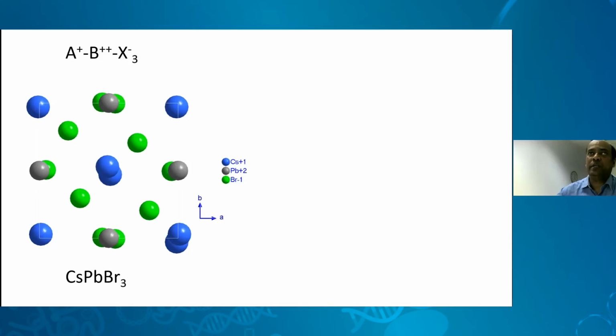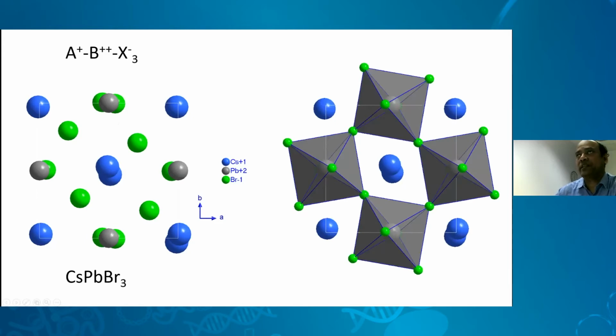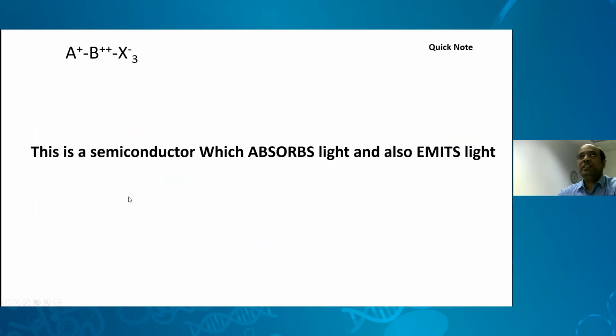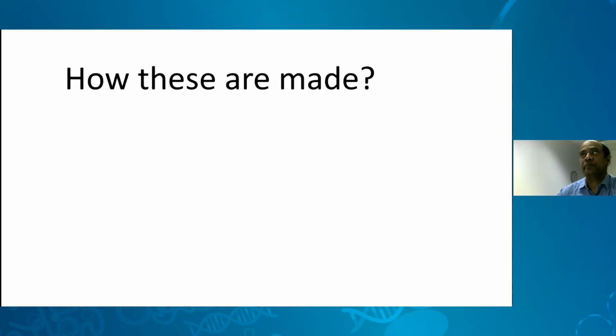These are the atom arrangements, what you see here. Scientifically it is put in terms of the lead octahedra, how they are surrounded. And the blue balls, what you see here, these are the largest atom in the periodic table, cesium, which remains here and is not bonded covalently. So now, in a simple way to understand, this is a semiconductor which absorbs solar light or light within the visible region, and also emits, which in the case of this particular material is green. By changing the halides, you can tune the colors from blue to red.